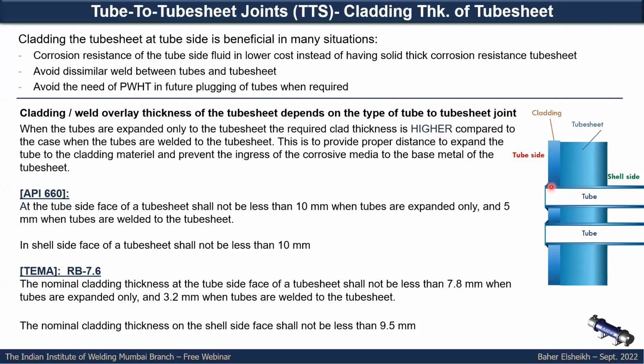But in welding, the sealing will be by the weld to the clad here, so you don't need much higher thickness. You need only thickness to respect the corrosion resistance and the dilution in the first or second passes between the clad material or weld overlay and the tube sheet. That's all. We will see the same applied in the two standards, API 660 and the TEMA standard as well. In API, they ask for 10 mm clad thickness in case you have expansion, and 5 mm in case you have welding. In TEMA, the same approach but different values. They recommend 7.8 mm for expansion and only 3.2 mm in case you have a weld.